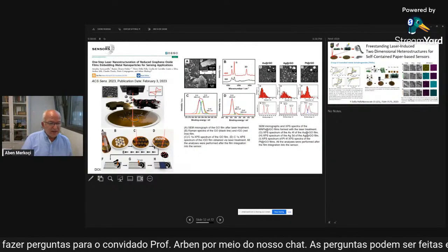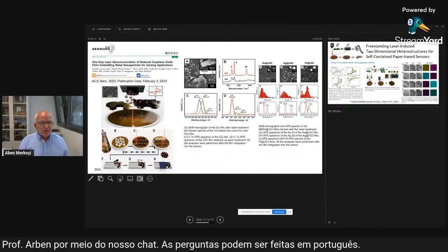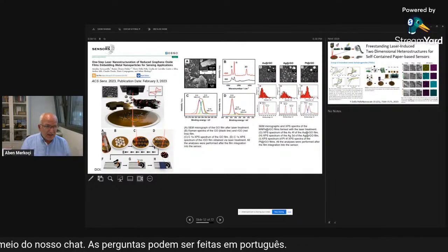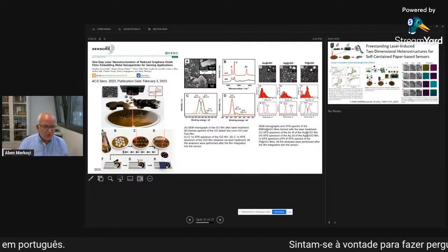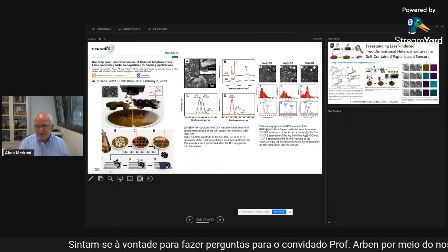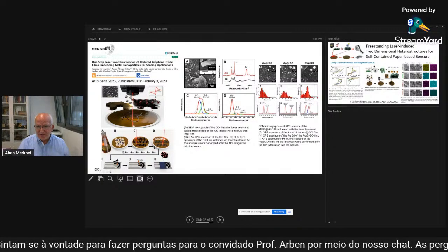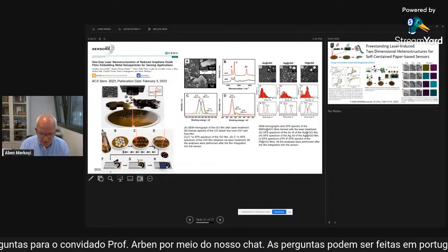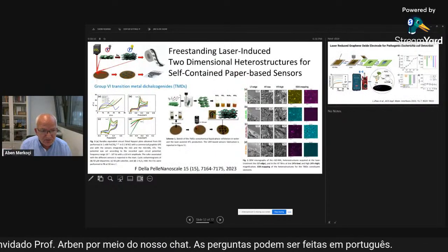This is an application of our graphene-based technique, but now improved by laser scribing, in which we apply the laser to graphene that is embedded with some precursors for different kinds of nanoparticles. So now on the surface of the graphene we have different kinds of nanoparticles, also gold, silver, platinum, depending on the application. Of course, after characterization, we're able to apply this for different applications.